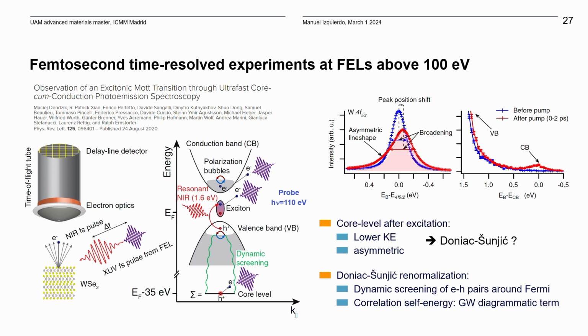So basically, before time 0, when your sample is in the ground state, you have a Lorentzian shape for the core level of tungsten 4f. However, upon creation of the excitons, there is a population of the conduction band, and screening effects start being very important. And what happens is that there is a drastic change of the line shape of your core level that can no longer be described as a Lorentzian or Voigt, which is the convolution of a Lorentzian with a Gaussian to take into account experimental resolution. Then you have to describe the system with a Doniach-Sunjic line shape,